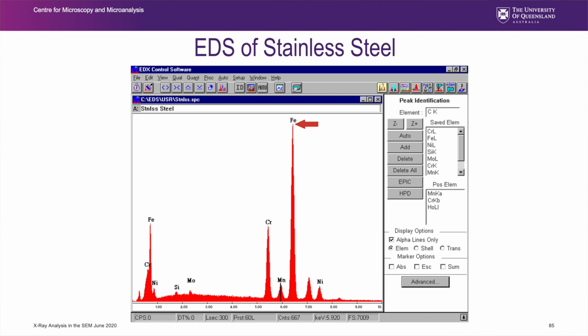If you look at the height of the K alpha to the K beta for the iron, and then you look at the height of the K alpha to the K beta for the chromium, this K beta peak, if it's the same K alpha to K beta ratio, which it roughly should be, they're very close transition metals, this chromium K beta peak is quite high given the height of the K alpha peak. So my interpretation is yes, there is manganese there, so I'm going to label it.